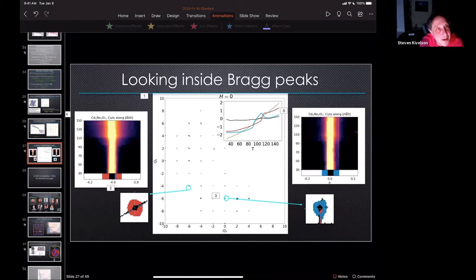That just gives you some sort of discrete symmetry. You're saying it's an approximate Goldstone. Yeah, but there is a continuous rotation that's possible between two structures. What we understand less is the very low temperature phase, which we believe has to do with the rotation of this axis, the principal axis, the primary direction. Really the order parameter has two axes, but there is an anisotropy, and the anisotropy is very weak. And there isn't a continuous symmetry to break, so there can't be a Goldstone mode, truly.